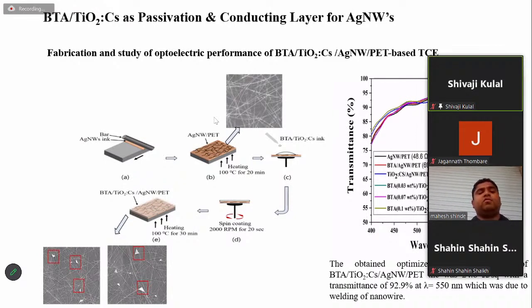I just put the ink on the substrate and coated it with a wire bar. As the wire bar is moved ahead, it coats the silver nanowire on the PET substrate. In SEM we can see the randomly distributed silver nanowire. After that, I used BTA TiO2 corrosion inhibitor and coated it on the fabricated electrode by spin coating, which is also a simple method.